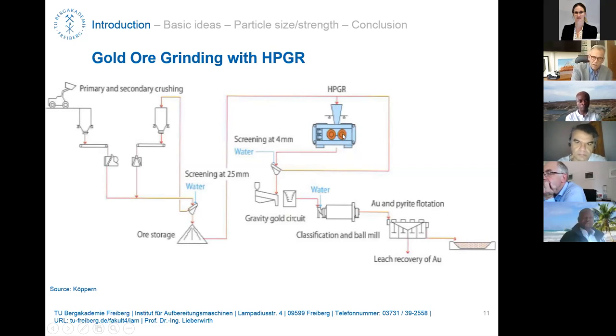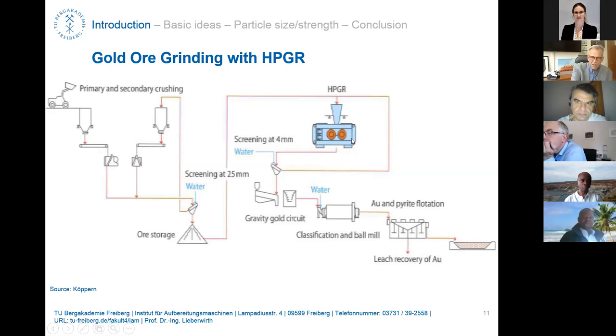So if we go to particle sizes way below 40, 50 microns, then the HPGR, with mainly just compression loads, may not be that efficient anymore. That's most probably also the case why you use the ball mill here in this gold application. And in cement grinding, clinker grinding, there are other reasons, with the particle size distributions of the cement, which is another important factor in the cement industry. But also in cement, usually you find HPGRs in combination with the ball mill for the finish grinding.